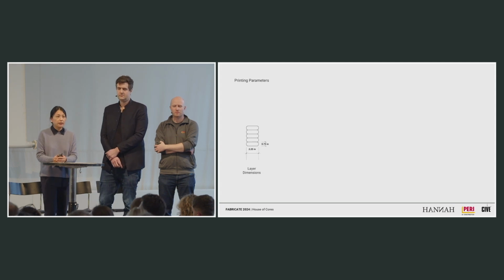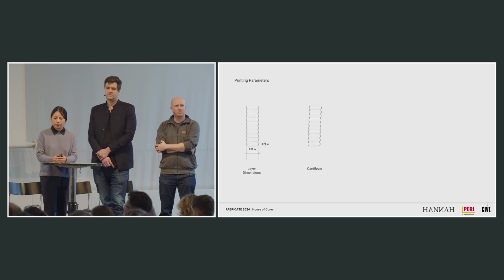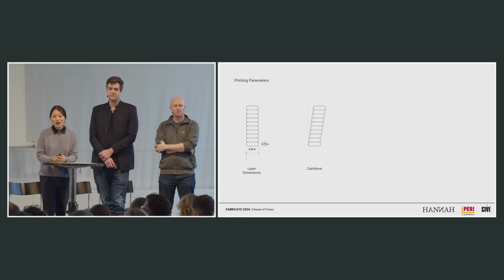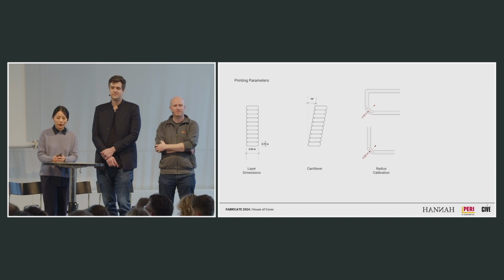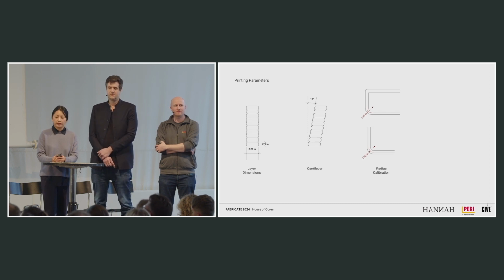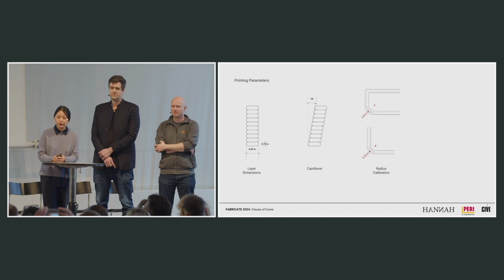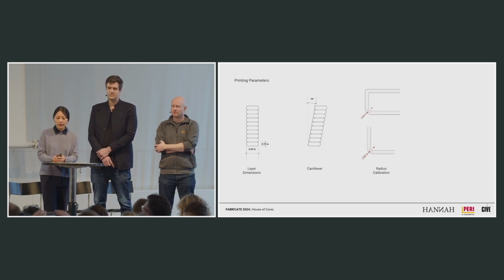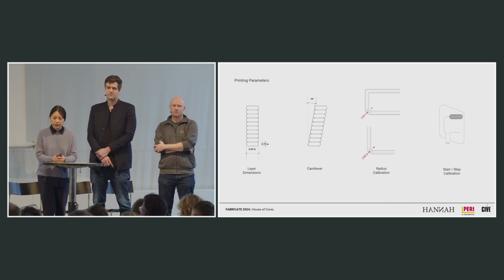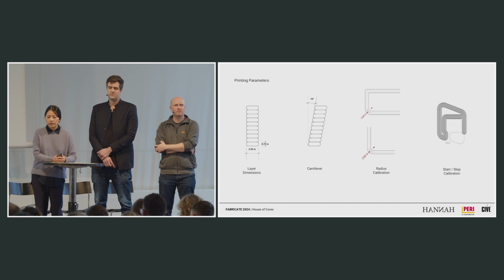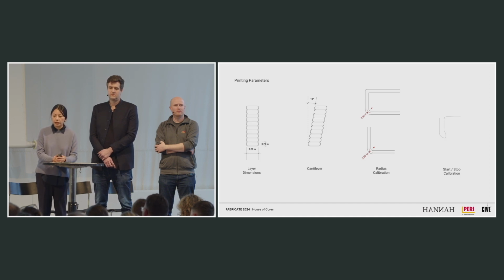And so key parameters for our project consisted of a layer height of, because we're in the US, 0.75 inch tall and a layer width of 2.25 to 2.5 inch, a maximum cantilever angle of 10 degrees, and dilating corner radii between 3 inch to 5 inch. And also using the centerline tube path calibration for start-stop positions during the printing process.